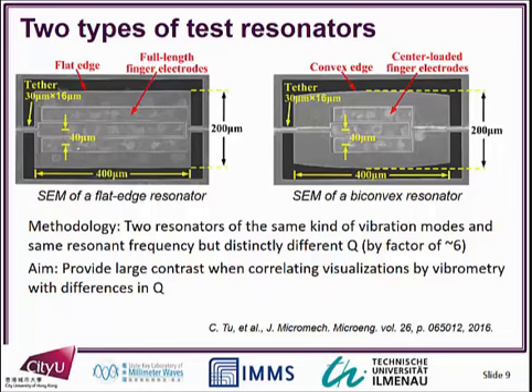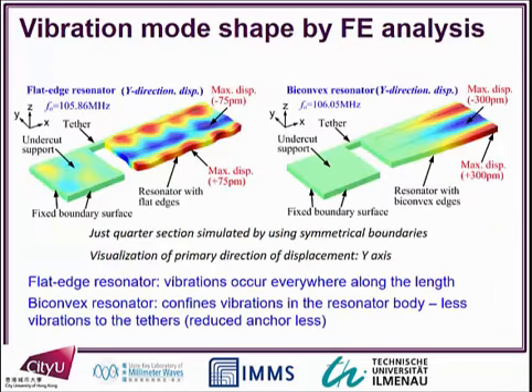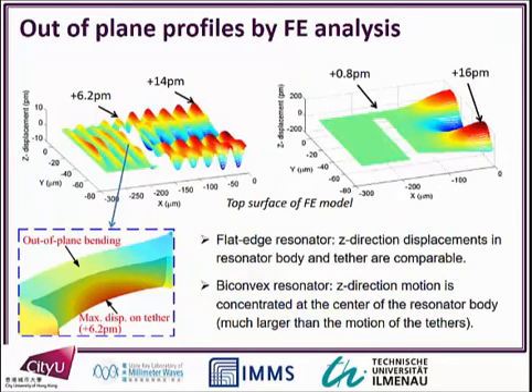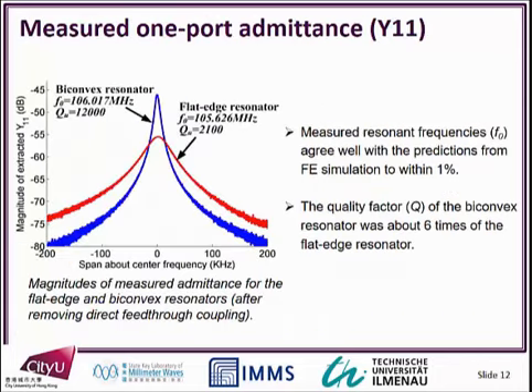Our aim was to provide some large contrast that correlates the visualizations from vibrometry to the differences that we see in measuring the quality factor. We can do some of this FE analysis to show that you do get this kind of concentration in the center, and that helps to raise the quality factor. If you do a scan on the z-axis, you see this kind of wave, and when you bend and curve these sides, you see this concentration, so it moves the waves away from the edges. This can be seen from FE. This bending over here is actually the beam bending up and down. Sometimes people say that the waves are coming out of that, but there is actually quite a bit of bending. So could we actually see these effects?